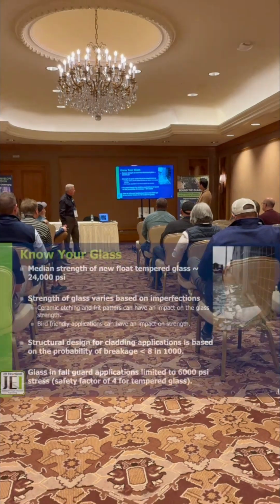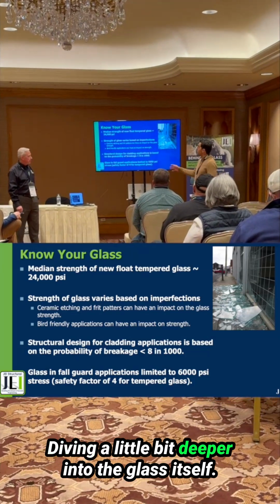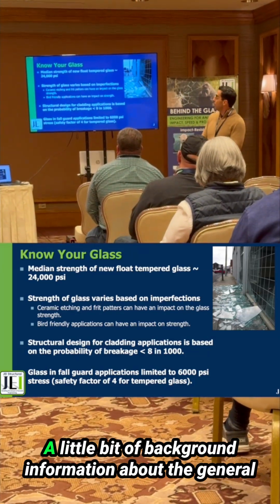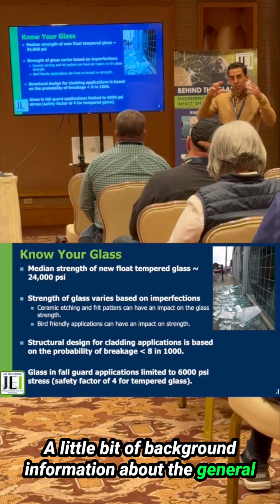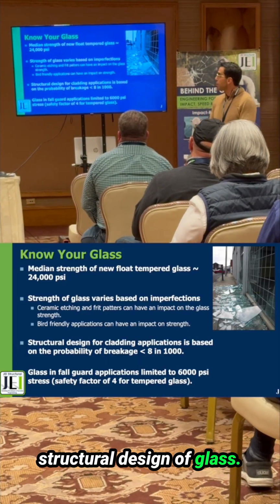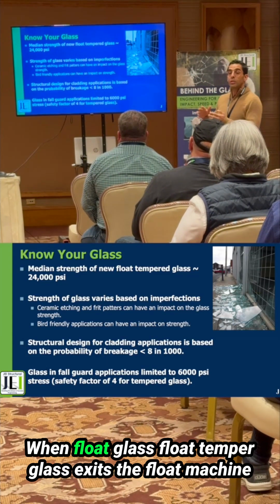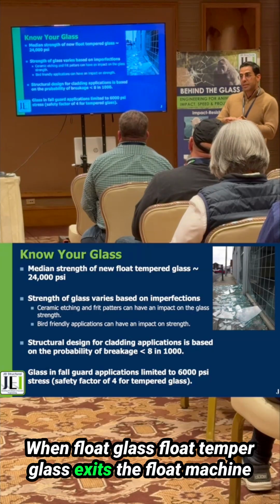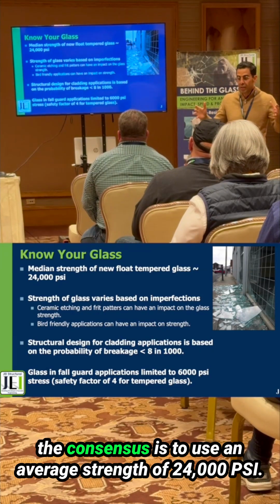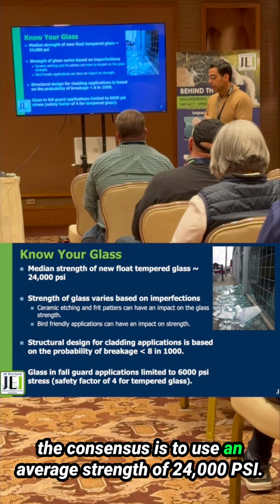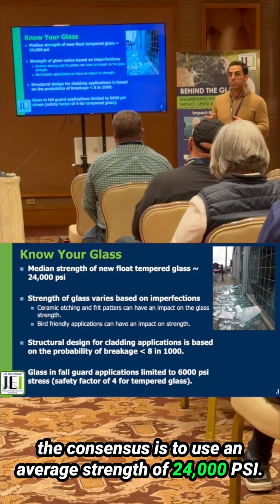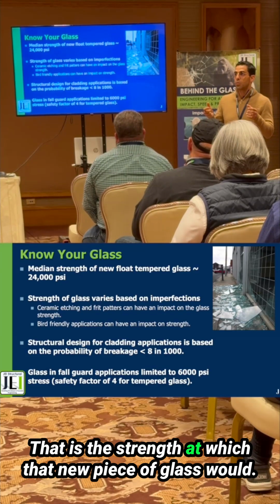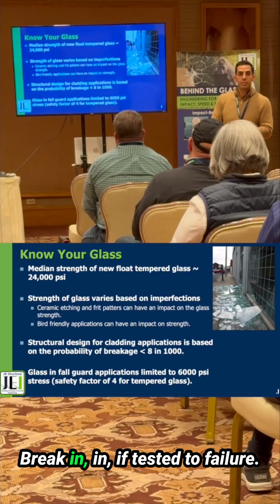Diving a little bit deeper into the glass itself, a little bit of background information about the general structural design of glass. When float tempered glass exits the float machine, the consensus is to use an average strength of 24,000 psi. That is the strength at which that new piece of glass would break if tested to failure.